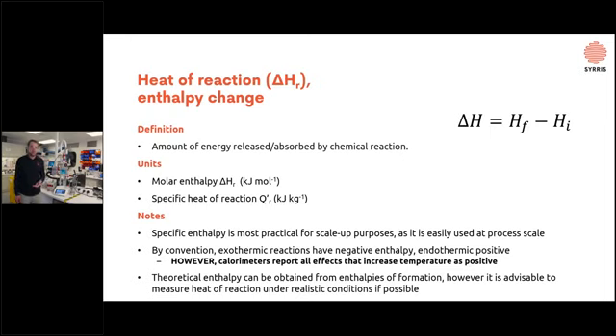endothermic reaction. And it's actually quite simple, because since we can't measure the enthalpy directly, we can only measure the change. So it's usually the final enthalpy minus the initial enthalpy. That's a very simple way to put it. For process development, the preferred way to report it is as a specific heat of reaction, in kilojoules per kilogram, because it's very easily scalable to different reactor scales, because it will be the same in a half-liter reactor and the same in a 100-liter reactor.